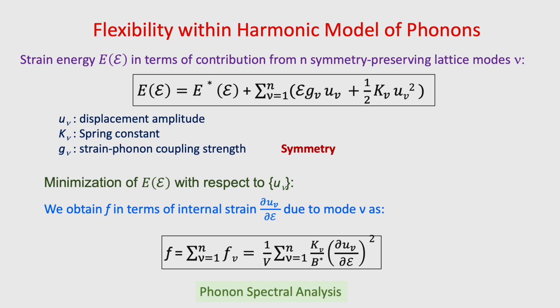Yeah, thank you. So we can also analyze this in a slightly simpler model picture, where we work with phonons in a harmonic model, and then you see the energy is written as elastic energy as a function of strain, and this is the key term which gives you coupling between strain and the optical phonons. Optical phonons are the internal degrees of freedom of a crystal. And then the last term is the stiffness of the bond, the optical phonon frequency squared.